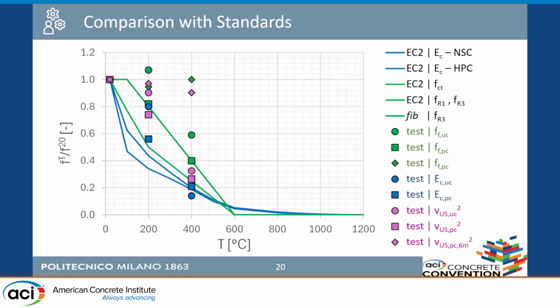that we can see here the round green circle represents the flexural strength. We see that we don't have any loss at 200 degrees C, and we have almost 40% loss of the flexural strength at 400 degrees C in uncracked sample. If we move to pre-cracked sample, we have the square, and you see that we are close to the curve suggested by the Eurocode. This is very important in my opinion.